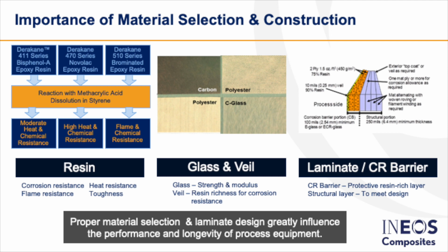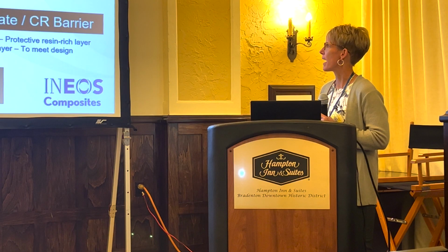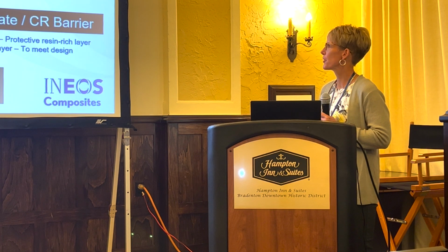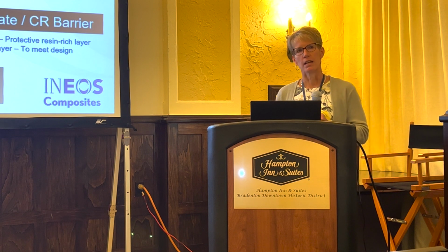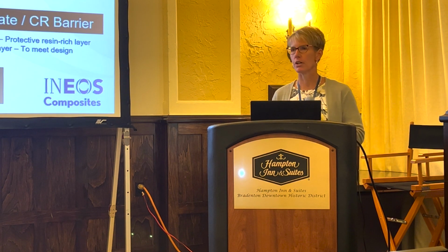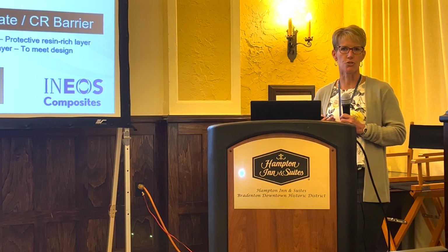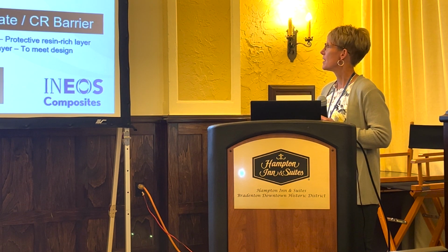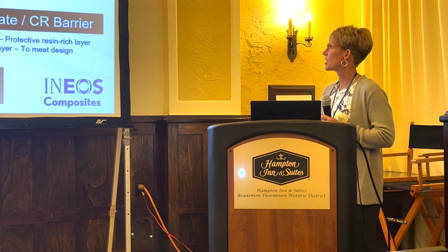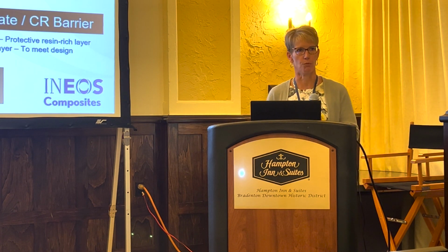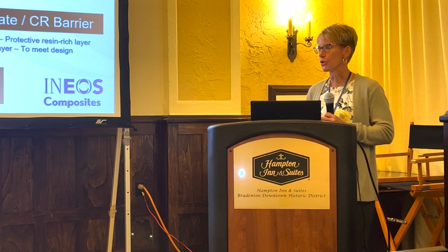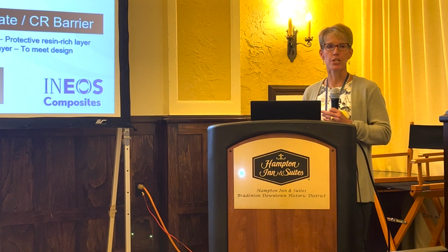Over here is a more detailed diagram of the laminate, starting with the innermost liner, your veil layer. As we talked about, that's a high resin content, usually about 90%, and then backed by 2 layers of the chopped strand mat. Together, that forms your primary corrosion barrier. Generally, it's going to be about 100 mils thick. Some environments require something thicker, maybe a chlorine environment or high concentrations of hydrochloric acid. And then behind that, your structural portion, which can consist of alternating layers of chopped strand mat and woven roving, filament winding, unidirectional, just depends on the engineering requirements for that vessel.